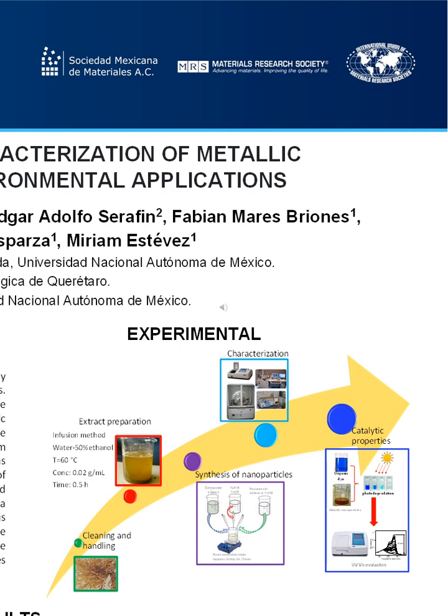The first consists of washing the sargassum to remove impurities. Then an extract is prepared by infusion, for which 1 gram of dry sargassum and 50 milliliters of a 50% water ethanol solution are used. The mixture is heated at 60 degrees Celsius and is kept under magnetic stirring for 30 minutes. It is allowed to cool at room temperature and is filtered.